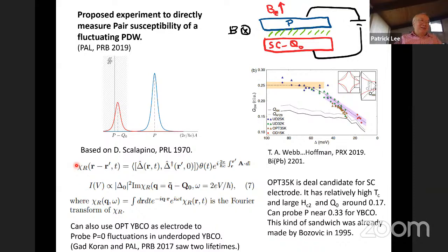Yeah, so I don't think there's a phase transition, right? But I would say it's BCS-like on the overdoped side, and underdoped is always complicated. It is BCS-like in the sense that you see a gap, you see a conventional d-wave gap. But at the same time, the 2 delta over kTC is very large, right? So there are signs that it's not like your ordinary BCS. But I don't think it's all the way over to a BEC. It could be some intermediate region. Thanks.